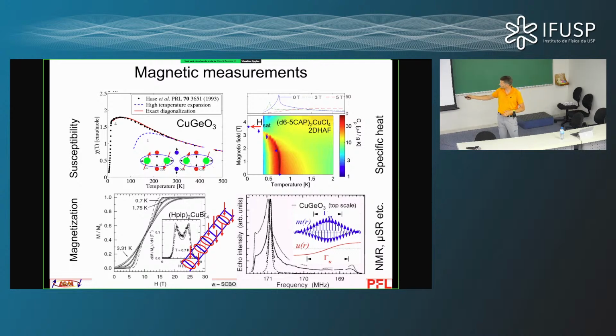We can measure susceptibility. So here's an antiferromagnet. We can see that because as we lower the temperature, susceptibility goes up a bit, but then it turns over, and then it suddenly drops down exponentially here. So I can tell just from this that there's a gap opening in the system. I'm forming such singlets that we mentioned before, which have no net magnetization. I can apply a magnetic field to such a singlet state, and eventually I will break the singlets and produce triplets, which are magnetizable. So I can magnetize the system. By doing this, I can say I have a system which in this case is a ladder or a chain of such spin pairs.